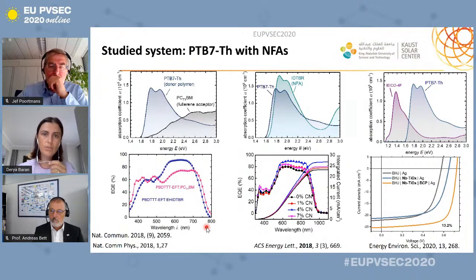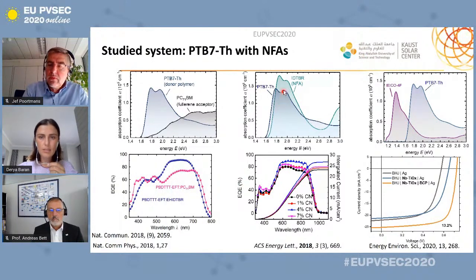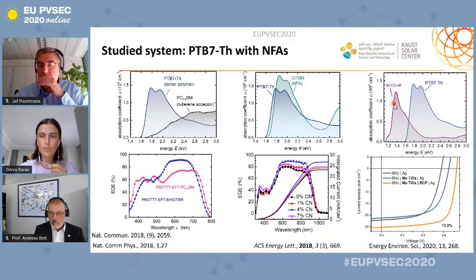But we quickly realized one beauty with these NFAs is that you can tune the band gap, and because these are push-pull type materials, not direct materials, you can cover a very selective region of the solar spectrum, rather than perovskites covering the whole spectrum and having a band edge, as you see here in the graphs. So as you see here, PC70BM and IDTBR have overlapping absorptions, which makes it very interesting because it still works as an 11-12% solar cell. Then we thought, what if we shift this NFA and design an NFA with a low band gap? What would happen?